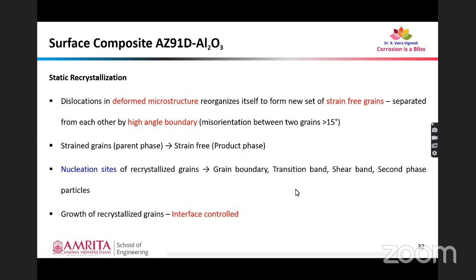Added to that, the nucleation sites for the recrystallized grains include the grain boundary, the shear band, and second phase particles. And the growth of recrystallized grains is interface controlled. Once we have more dispersion of second phase particles, obviously the growth of recrystallized grains will be restricted. Since we have added nanophase alumina into it, obviously we'll end up with restricted growth in recrystallized grains.